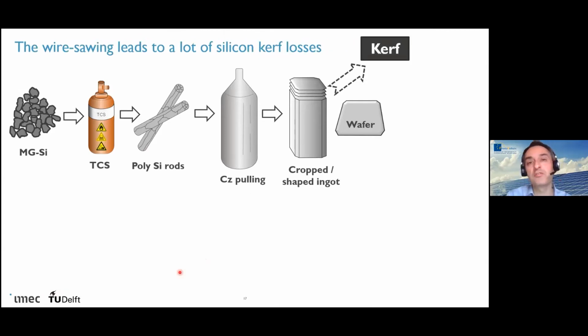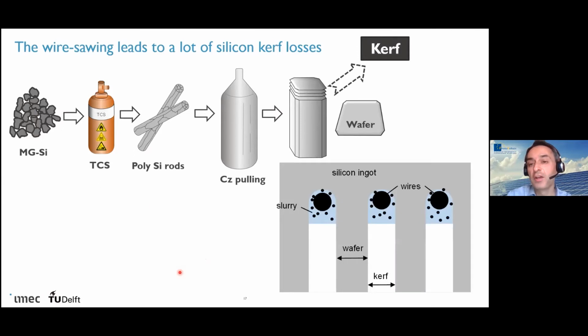Now, one downside of this process is that you create a lot of kerf losses. What does it mean? So we make wafers of 180 micrometers thick, but there where the wire is actually slicing, you actually lose typically around 80 to 90 micrometers of silicon.